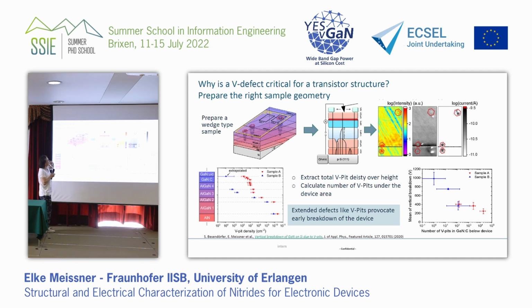And we can see this if we count the number of V-pit dislocations underneath the area of the device. And then you need something extra, which I haven't talked about. You need clever sample preparation. Because samples with the layers in the cross-section have very thin layers, so how can you observe it? We geometrically widen the structure. Geometrically widen means you cut with an inclination through it. You create a wedge-type sample. And then you can observe the V-pits over the height of the sample, which means over the height of the layer stack.